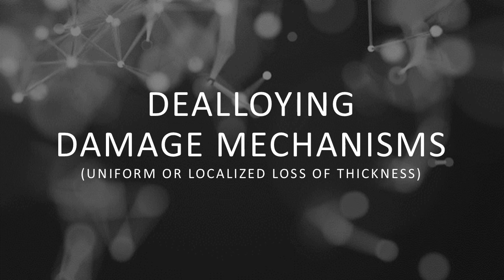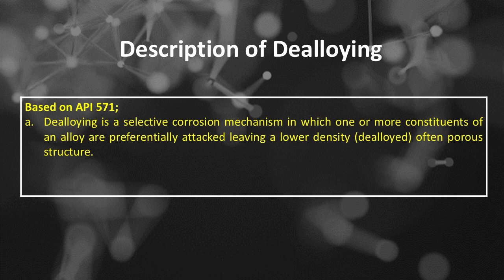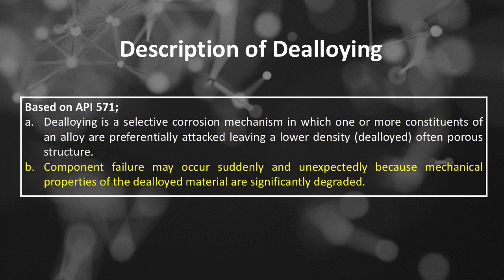Dealloying damage mechanisms as a part of uniform or localized loss of thickness. Description of dealloying based on API 571, Number A. Dealloying is a selective corrosion mechanism in which one or more constituents of an alloy are preferentially attacked, leaving a lower density, dealloyed, often porous structure. Number B. Component failure may occur suddenly and unexpectedly because mechanical properties of the dealloyed material are significantly degraded.